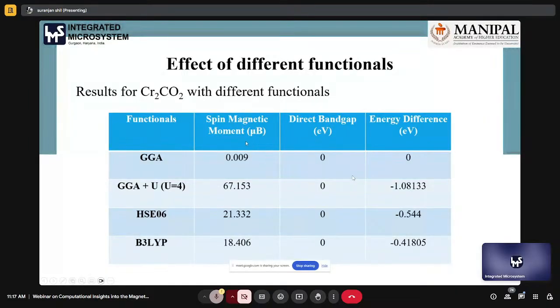So what we found in spin magnetic moment is that with GGA, we find very low magnetic moment, and the energy difference between the parallel spin and anti-parallel spin configuration is 0. That means it shows a non-magnetic behavior. But the other methods all show a ferromagnetic behavior, which matches with the literature value. So we go with HSE06, the hybrid functional, which is reported to give good magnetic properties of materials.